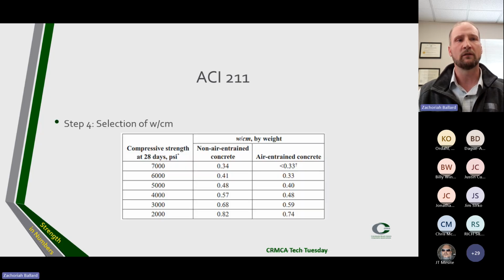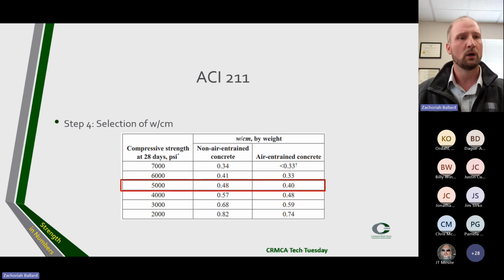Step 4 is the selection of our water cement ratio. The required water cement ratio is determined not only by strength requirements, but also by factors such as durability. Because different aggregates and cementitious materials may produce different strengths at the same water cement ratio, it's desirable to have or develop the relationship between strength and water cement ratio for the materials to be used. So in our example here, we're going to do a 5,000 PSI concrete, non-air entrained. So that gives us a starting water cement ratio of 0.48.